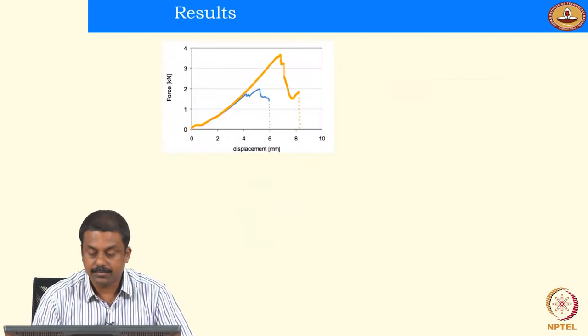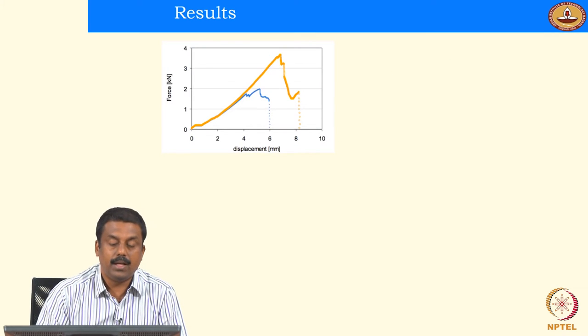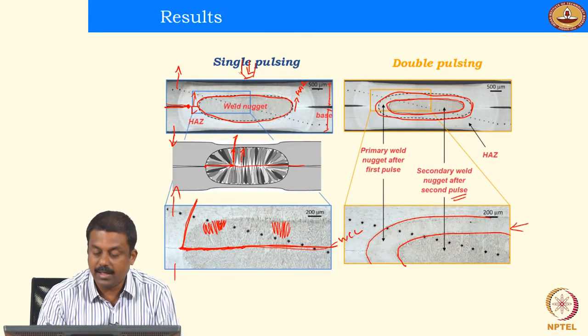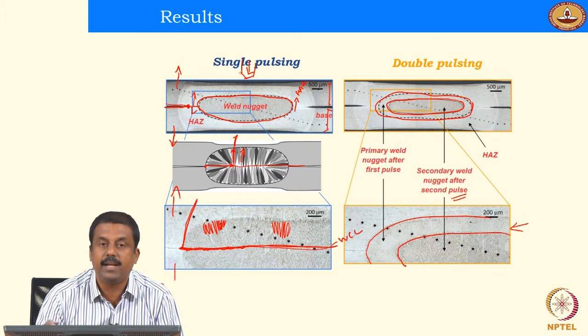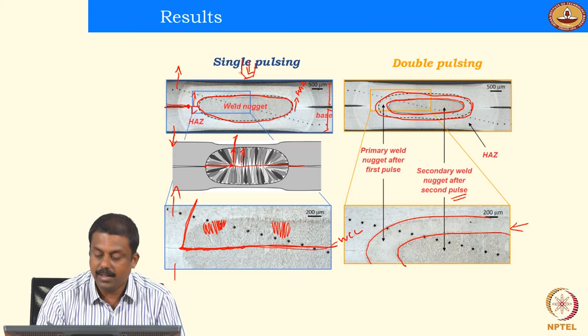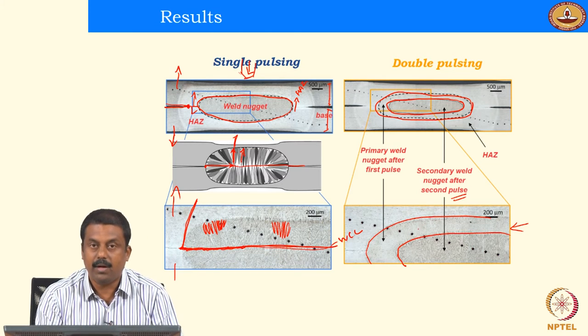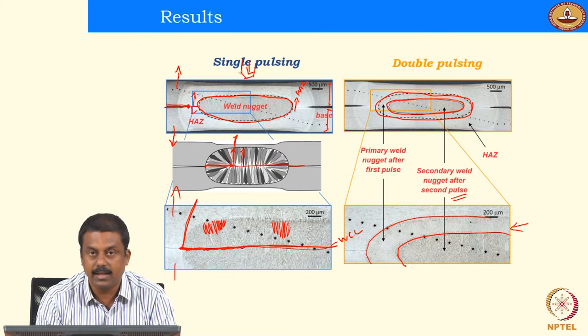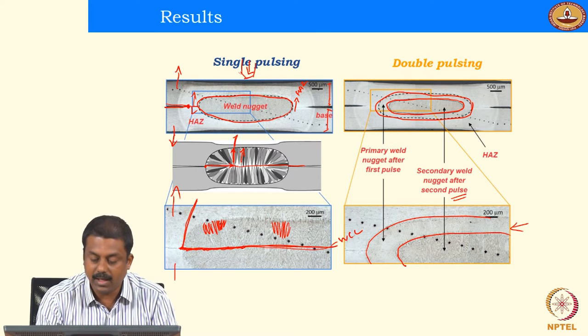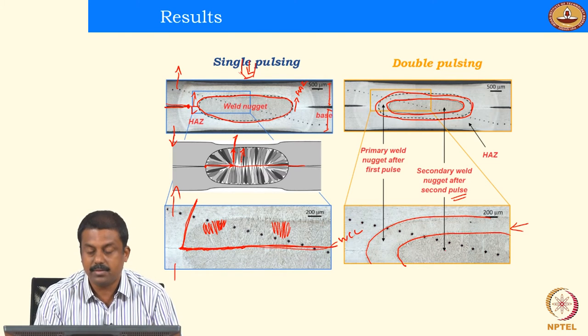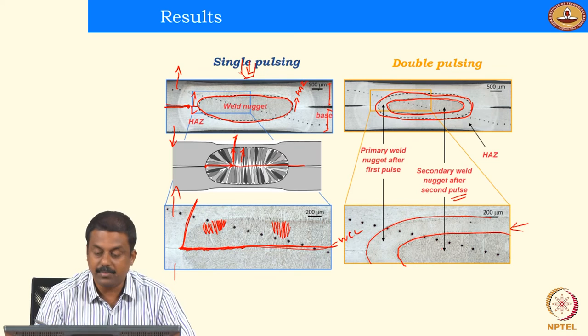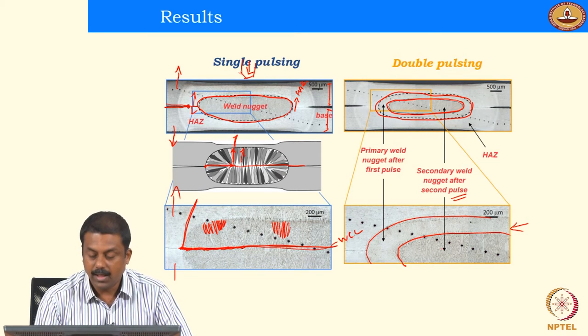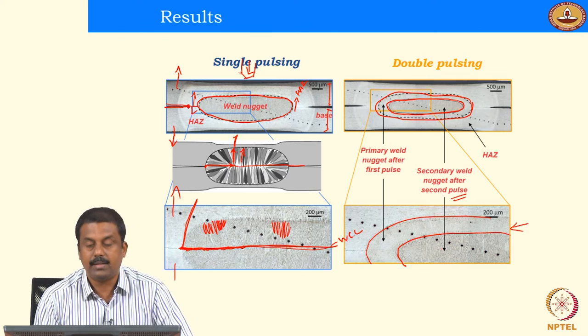And this can be beneficial. Basically, what you do here by applying second pulsing is a heat treatment of the weld nuggets which are formed by the first pulsing. Okay, so you apply a second thermal cycle, which can do a homogenization of the regions somewhere over here, for example, or because of remelting, you may also have segregation effects reduced in the regions. We will see in the subsequent slides what happens chemically when you are applying a second pulsing.